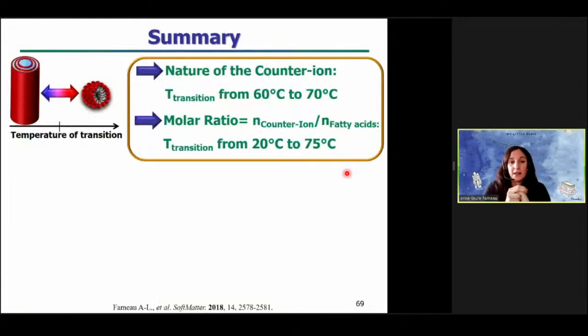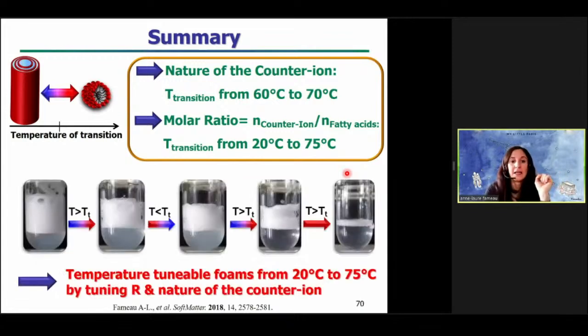So in summary, just by tuning the nature of the counterion, you can tune the temperature transition from 60 to 70 degrees. But the best parameter is really the molar ratio, because by tuning the molar ratio and the nature of the counterion, you can have a wide range of temperature transition from 20 to 75 degrees. And then we checked that we can really have temperature tunable foam for this wide range of temperature. And yes, we can have temperature tunable foam from 20 to 75 degrees. You just need to choose and combine the right counterion with the right molar ratio, and you can destabilize the foam on demand at the temperatures that you want. And this is very useful for a lot of industrial applications.